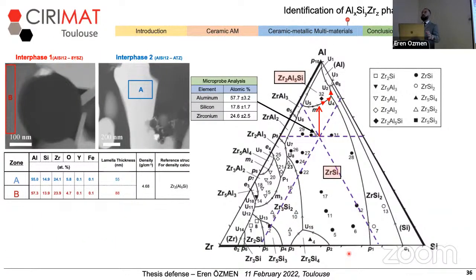So I wanted to check if the creation of this ternary phase is possible in this environment. When I take the elemental distribution from microprobe analysis and apply it on the ternary phase diagram among aluminum, zirconium, and silicon, I see that the area already corresponds to the intermetallic phase.